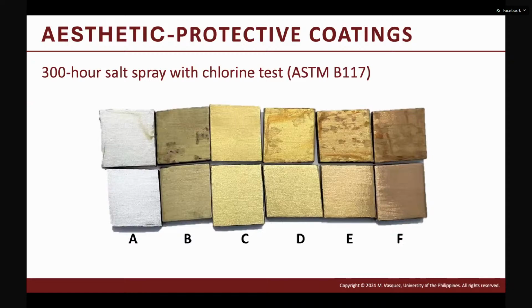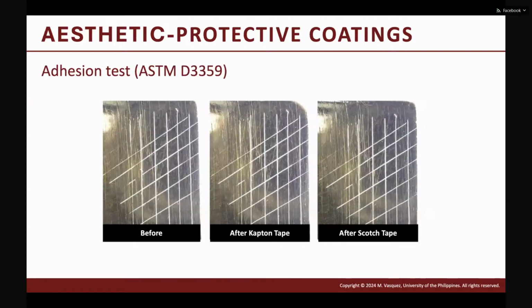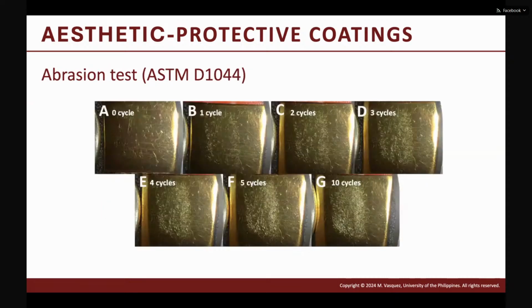We did a salt spray test with chloride, because one of the interested users of this technology are companies or, let's say, resorts that are located along the beach. They have a really big problem with corrosion because they are near the sea. And we have also tested its adhesion properties. So we have really good adhesion between the coating and the substrate. Also abrasion, it's not really abraded.